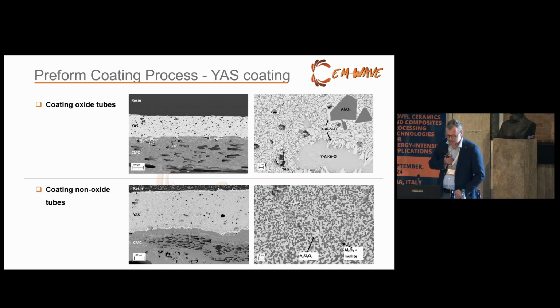And we show you here some results on the final coating of our preform tubes by using a YAS system. Here you see the cross sections for the oxide tubes and the non-oxide tubes using the YAS. Again, the advantage is to use the same YAS system for completely different ceramics, and as you see, it worked quite well. If you have any questions about the coating process, please ask Jonathan Meyer, he is here today, for more details.